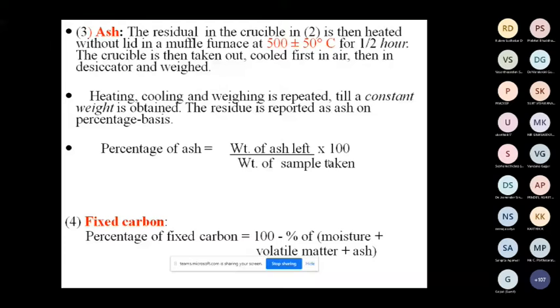Once it has entirely become ash, cool it first in air and then in a desiccator. Heating and cooling may be repeated till constant weight. Then find out the percentage of residue, that is ash. Weight of the ash times 100 divided by the sample weight gives you the ash content.